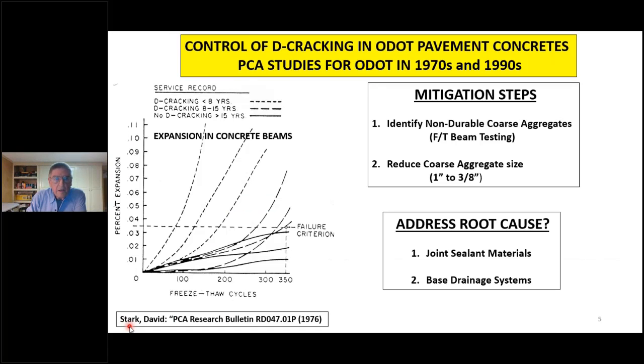Okay, there we go. One of the things that the PCA workers did was come up with the beam tests, where the concrete beams containing aggregates with different service records with respect to D-cracking were tested. And of course, you're probably all familiar with this, the ones that showed early D-cracking also had early and very high expansions in the freeze-thaw test, which went on for 350 cycles. The failure criterion at that time was about 0.035%.